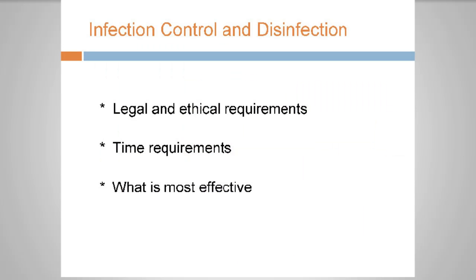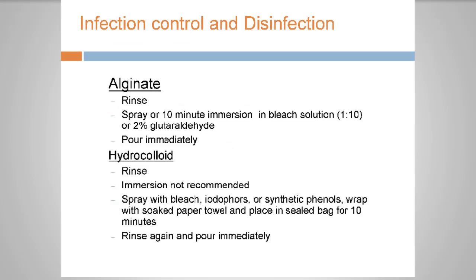There are some legal requirements that we have to meet. We have to disinfect. There's also what's going to be most cost effective. So I went back and forth between the manufacturers of the disinfecting solutions and the impression-making people, and I asked them, what do you disinfect with? And they say, go see the disinfecting people. And I go to the disinfecting people, and they tell me, see the impression people. So I got really frustrated with it, so I basically came up with what you should disinfect with. If you're using alginates, it's basically a bleach solution. Hydrocolloids, you can use a bleach spray, wrap it up, soak it in there for about 10 minutes, and then rinse it off and then pour it up.